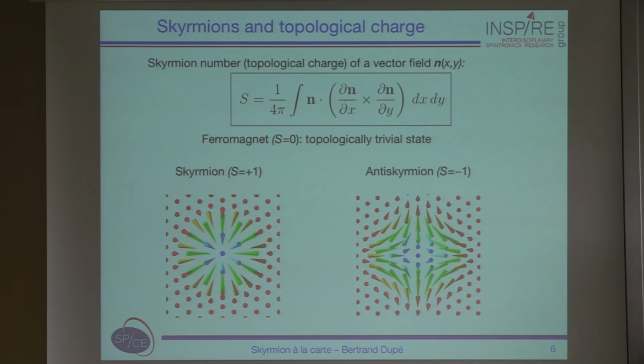Now there is another object, which is also very interesting, that Stuart Parkin introduced Monday morning. It's the anti-skyrmion. The anti-skyrmion does not carry a charge of 1, it carries a charge of -1. The difference between this object and this object is that when you go from the ferromagnetic background to the center, depending on where you start, you don't have the same rotational sense. On this axis, for example, you have what we call a right-rotating spin structure, and on this one you have a left-rotating spin structure. So sometimes these objects are also called achiral skyrmions, because they don't show this unique rotational sense, and they have a charge of -1.